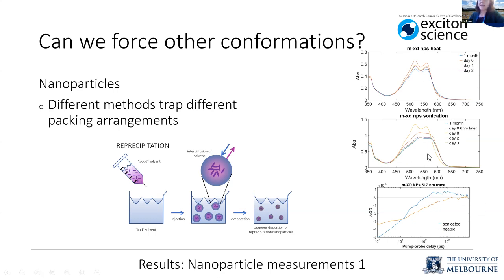And what I found is that in this case, we do see a long-lived bleach. It's a bit of an absorption too, but we see that there are signals that could be associated with a long-lived triplet that we don't see in the heated equivalent where you don't have that J aggregate peak. So that was pretty interesting.